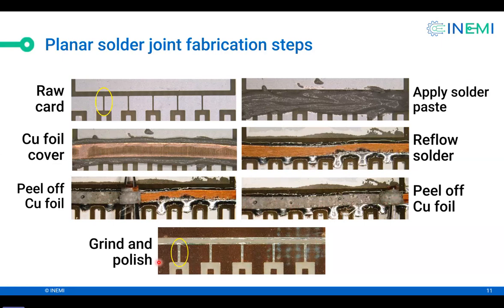And the last step is we grind this specimen, then we polish it, and we get 1, 2, 3, 4, 5 solder joints. And we can pass current in series. So we get results in one swoop. We get results of electromigration in 5 solder joints. Now we can vary the width of these, or the length of the solder joint. Length is in this direction, width is in this direction, and the thickness is into the paper. And we have tried different lengths of solder joint. Presently, we are using 0.2 millimeters.